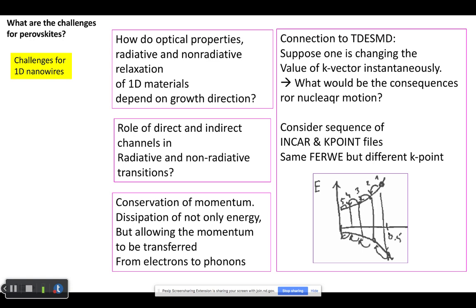If one excites at a non-zero k vector and one has only HOMO and LUMO, it doesn't stay at the original momentum, but it jumps down to the gamma point or whatever the minimum in the dispersion law is for both electrons and holes. So it is the basic process that we do want to mimic. So, a little incremental indirect transition with loss of momentum into lattice vibrations.